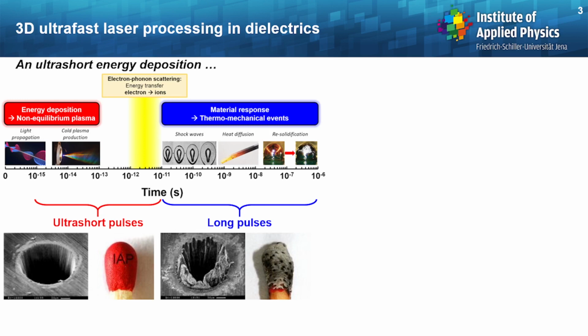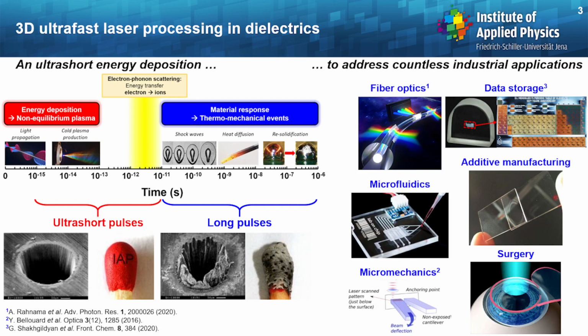All right, so to put everything in context, it will probably be a secret for no one here that ultrashort lasers represent an extraordinary tool for modifying materials. And the reason is contained in this figure, because at those extremely short pulse durations, below a couple of picoseconds, it is possible to separate the causes, which are related to the energy deposition, from the consequences, which are related to the material response, as illustrated here. And this provides a fantastic degree of control on the modifications you can achieve in dielectrics, especially in glasses, leading to a lot of applications in fiber optics, in surgery, also in microfluidics, micromechanics, in data storage as well.